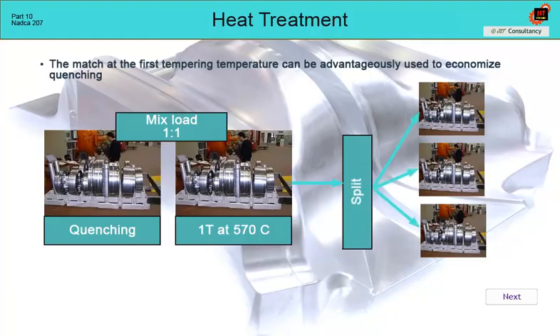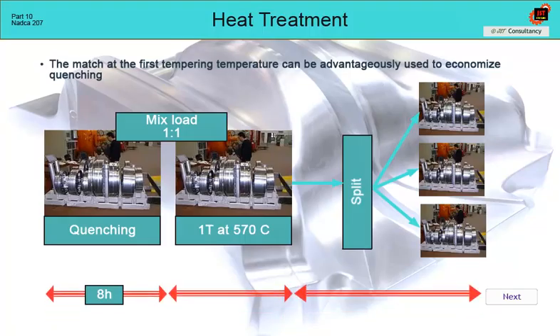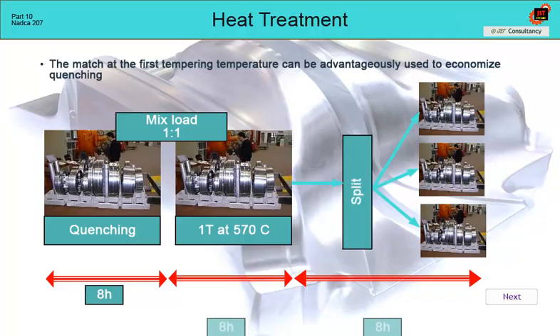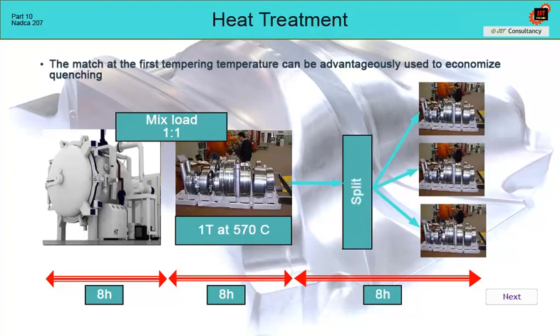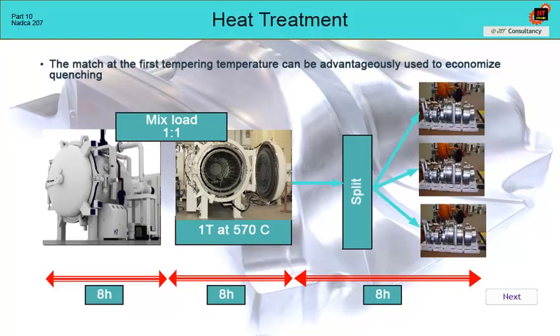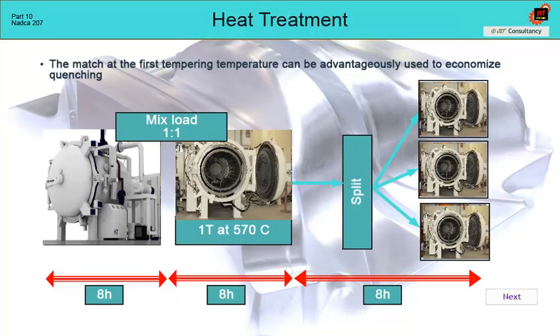Since the hardening cycle and each subsequent tempering can be carried out within 8 hours with some optimization of the batches, the entire process with 2 temperings can be completed within 24 hours. This is very important for tool shops. It also follows that for each hardening furnace there must be at least one vacuum tempering furnace of the same dimensions as the hardening furnace. Only after the batch has been divided for the second tempering can smaller furnaces be considered.